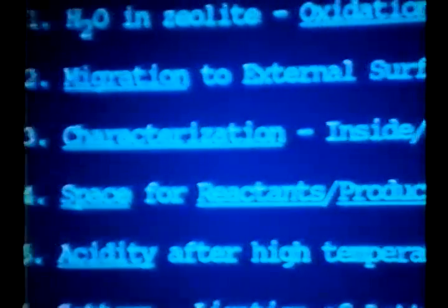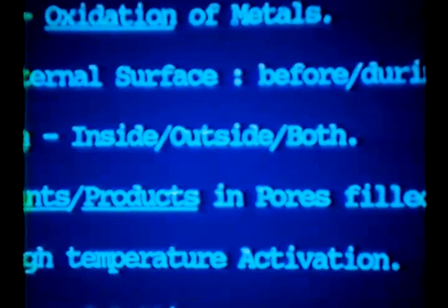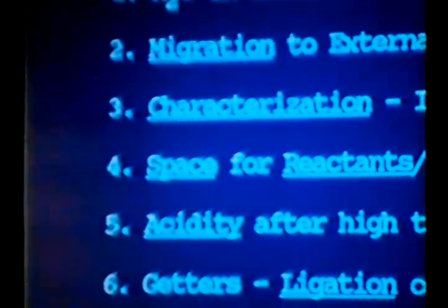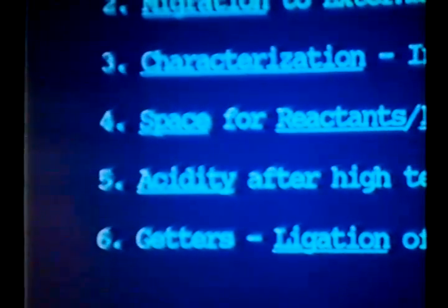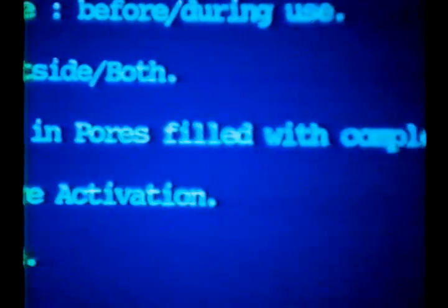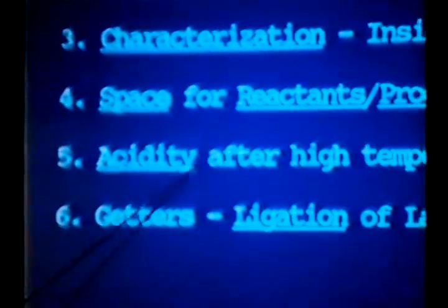One of the big problems in this area is characterization. It's pretty difficult to tell whether a metal's inside a pore or outside a pore or both. And that's an important problem. If you put a large molecule inside this pore and you fill it up, then it's going to be difficult to get a reactant in and out, potentially. So that could be a problem. If you heat the material to fairly high temperatures, 300-400 degrees centigrade, the material can become acidic, and you may or may not want that. So that's another parameter we'd like to try to control.